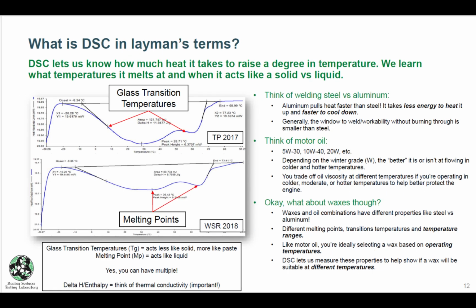So what am I really talking about? Maybe some of you are familiar with welding aluminum versus steel. You see that aluminum is relatively more difficult to weld than steel without a lot of practice. Part of the reason is that it takes less energy to heat up and it cools down faster. So aluminum, you can heat up really quickly and it'll cool down really quickly. If you were to do the same thing to steel, you'd see that the steel would heat up more slowly, and then of course it would cool down more slowly. So there's this window when you're talking about welding and workability where you would potentially burn through the aluminum if you were using the same method that you were using on steel.